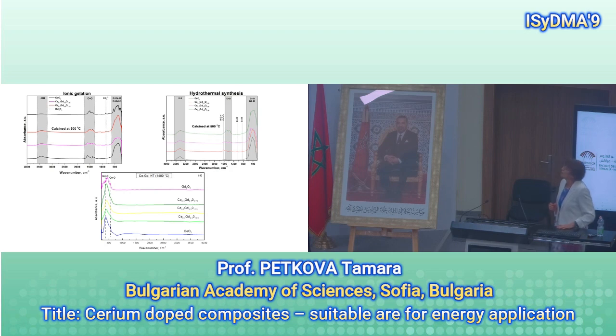To study the structure of this material, we use several methods. First one is the infrared spectroscopy. And what we found for the samples obtained at 500 degrees centigrade and from hydrothermal synthesis is that, again, except the peaks of cerium with oxygen and gadolinium with oxygen, we found peaks that belong to hydrogen with oxygen that comes from water, and also some peaks of carbon and oxygen. Maybe they come from the air, or probably from some traces of potassium carbonate, which is the product of the ionic gelation reaction.